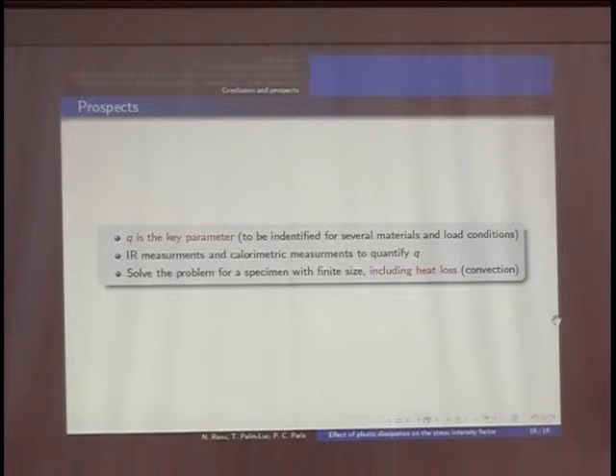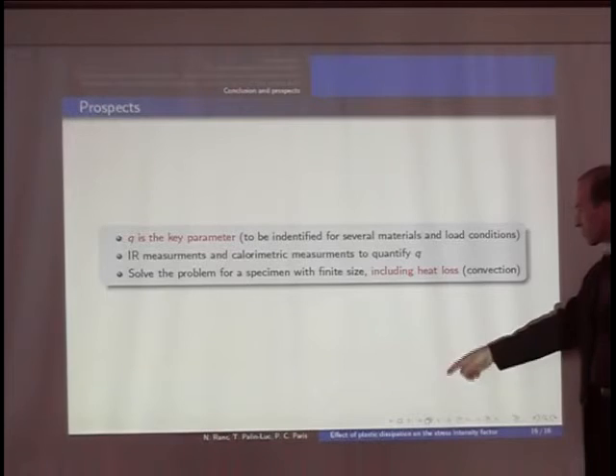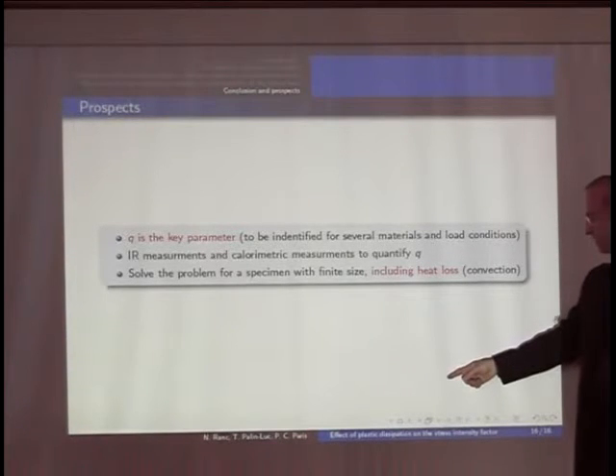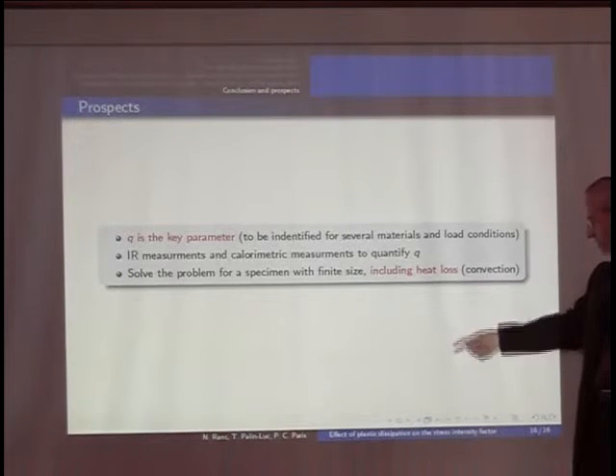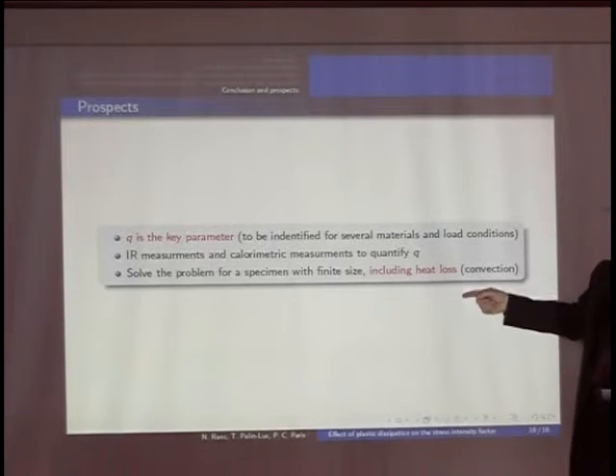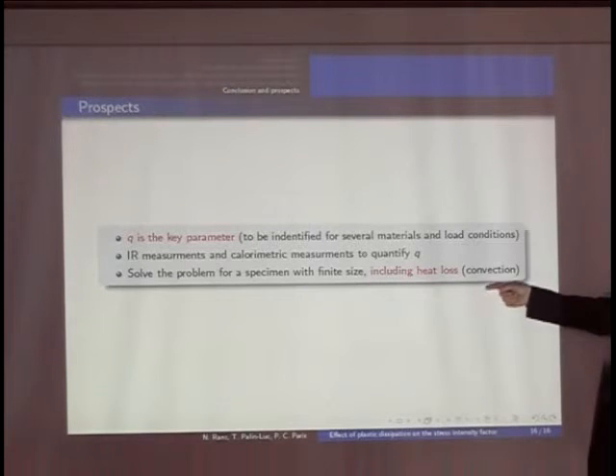They are always even at 20 kilohertz in the near threshold region was so small that we could not really... I understand what you mean there. I see. In what you say, there are two important things, if I correctly understood, but you can correct me. The first thing is that it's clear that we have no board here, but in fact, if you look at the temperature versus time, there is a curve with a thermoelastic effect at high loading frequency, and there is a monotonous constant increase.